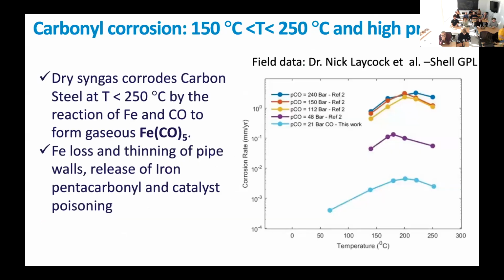Another problem: this was a topic we worked on for 2 subsequent projects, done with the Hamad. Then we had a 3rd project with Shell. At this time, they had another problem. The problem was happening at much lower temperatures, between 150 Celsius and 250 Celsius, but at high pressure. And what they noticed is that dry syngas corrodes the carbon steel.